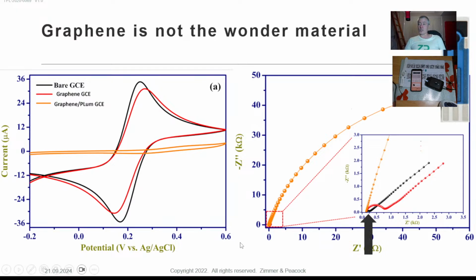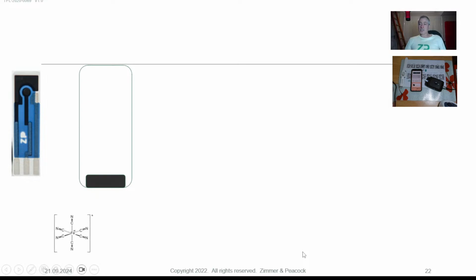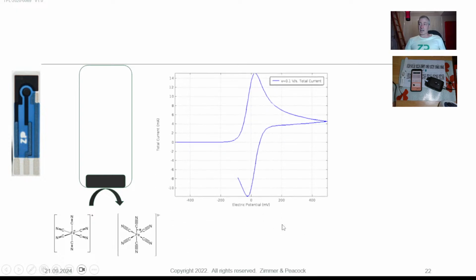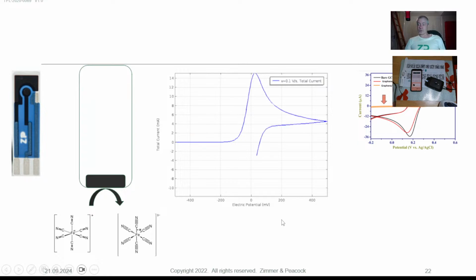and that would actually suggest that you're not exchanging electrons with it, because you lost all your voltammetric signal, and your charge transfer resistance between polyluminol and the ferrocyanide was 120,000 ohms. So your own data is backing up what I'm saying. In the presence of graphite or graphene, you are getting a good exchange of electrons, and you get a decent enough cyclic voltammogram, but it all shuts down when you do the polyluminol, because the polyluminol is probably coating the surface as you intended.